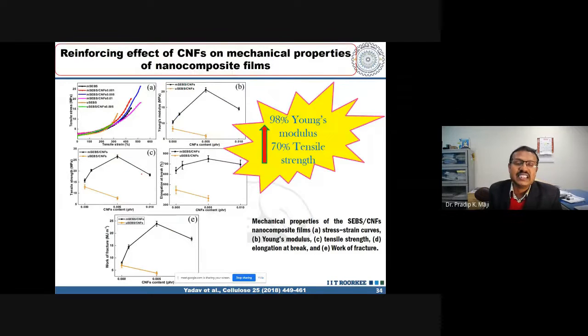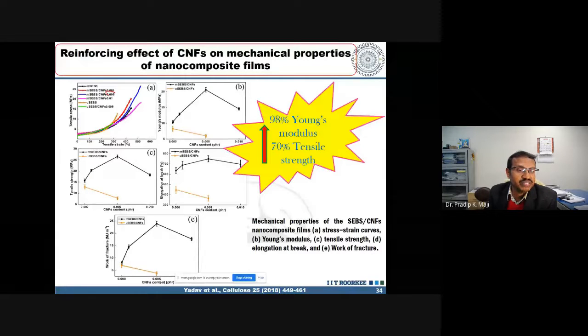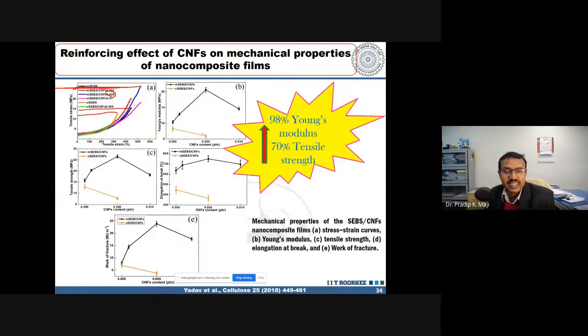After seeing this interaction, we have to check the mechanical property of our material. We have checked it, and you see 0.0058% material is giving manifold mechanical property improvement over that of normal SEBS. Almost 98% Young's modulus increment and 70% tensile strength increment has been reported.